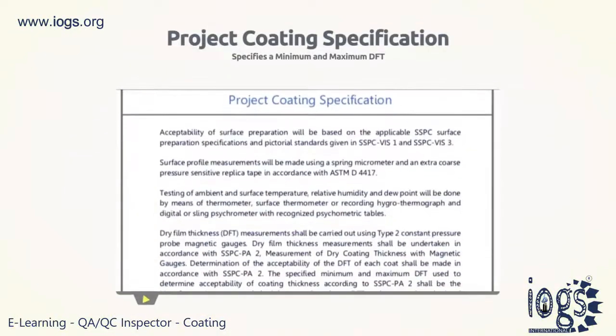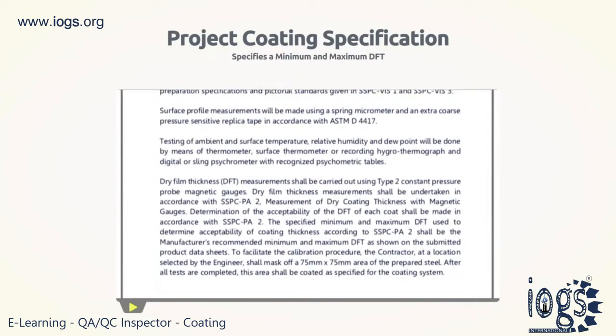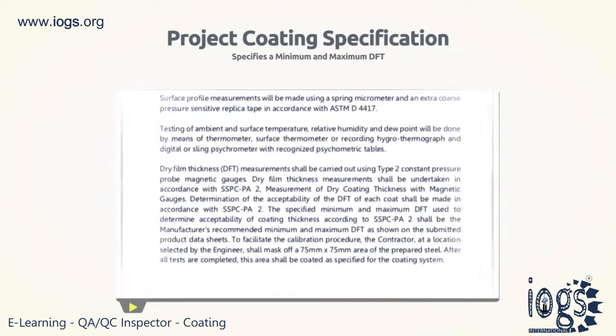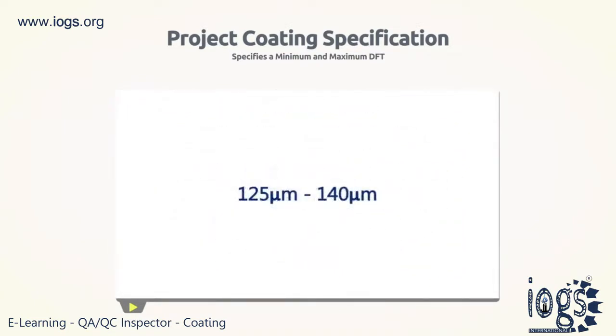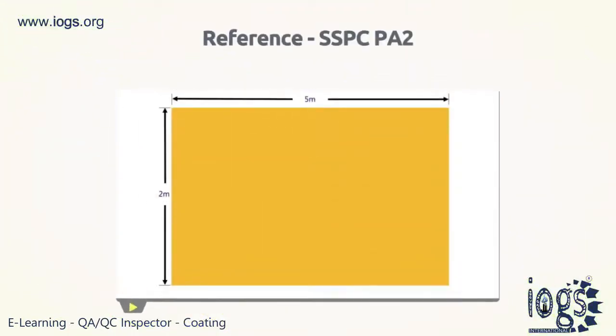The project coating specification will determine the dry film thickness value of a coating system to be measured. That is both the minimum and maximum coating thickness value. However, if a coating specification specifies a single DFT value, then the specified thickness would be considered as the minimum. If a 10 square meter area of dry film thickness is to be measured, the inspector is expected to select 5 random spots and measure the same. Each chosen spot must consist of 3 gauge readings that do not exceed the 1.5 inch diameter circle.